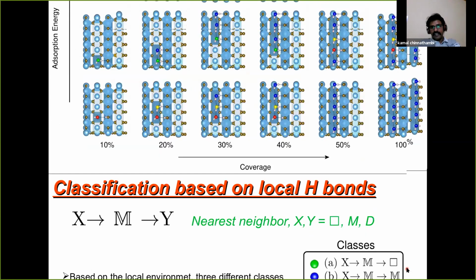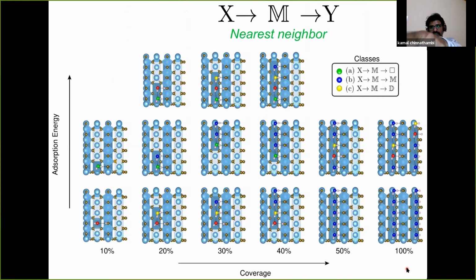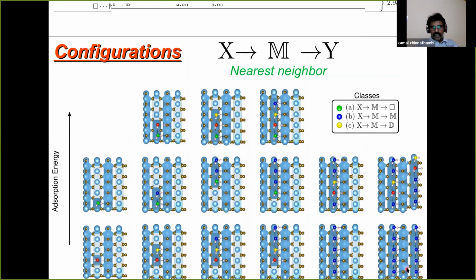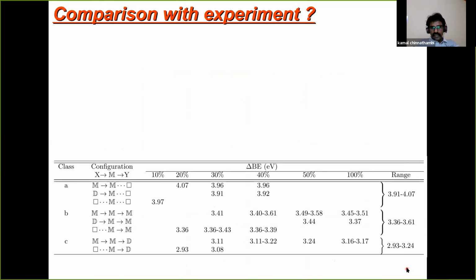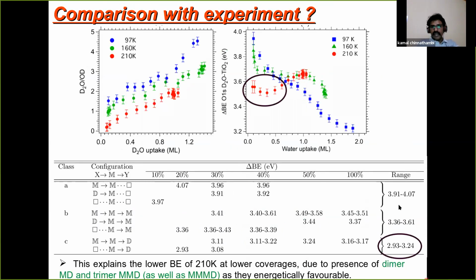Now you can see why there is color coding, because these molecules correspond to different classes depending upon their neighbors. So now I will come to the experiment. Why are we getting this lower value? Because at the lower coverages, a high degree of dissociation at 210 K is the most probable one. That is what we see from the adsorption energy calculations.